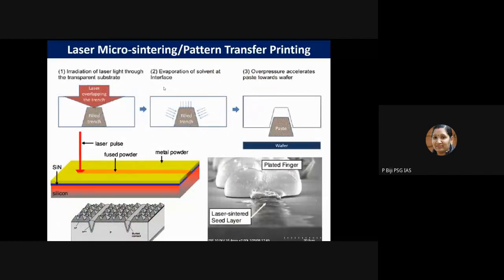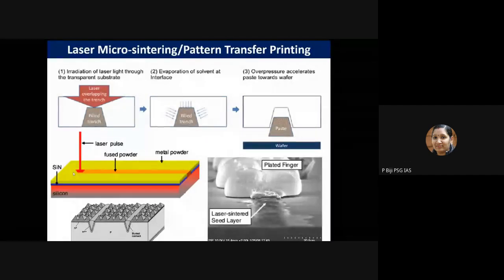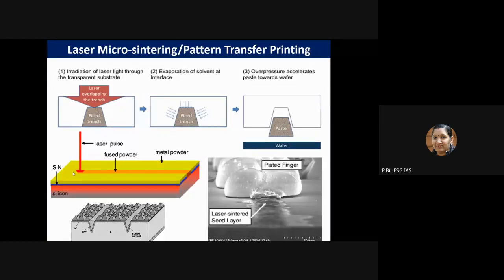The next important technology is laser micro-sintering. Laser micro-sintering is basically a rapid prototyping technology. This is used to create three-dimensional objects by a layer approach. In this case, a laser is applied to fuse a thin layer of the powder material spread on the solid object, as you can see in this schematic. Metal powder will be spread on the wafer, and the laser falls on the surface. This laser beam with appropriate energy scans over the powder bed. So the metal powder is sintered and bonded to the emitter surface.